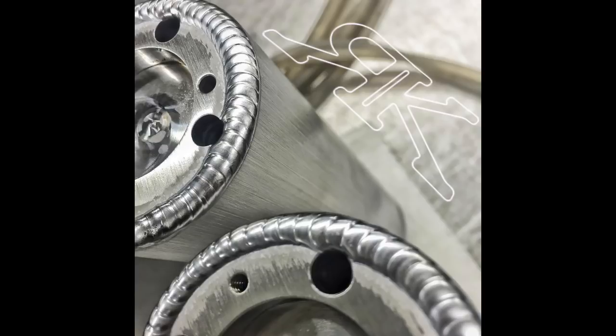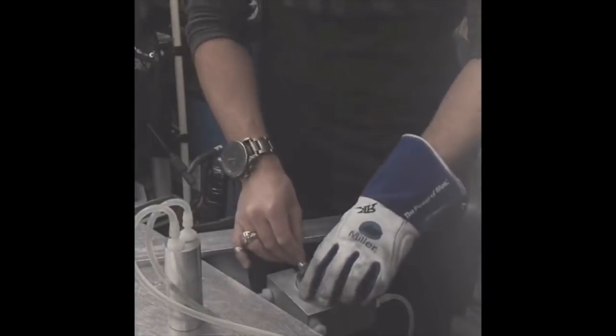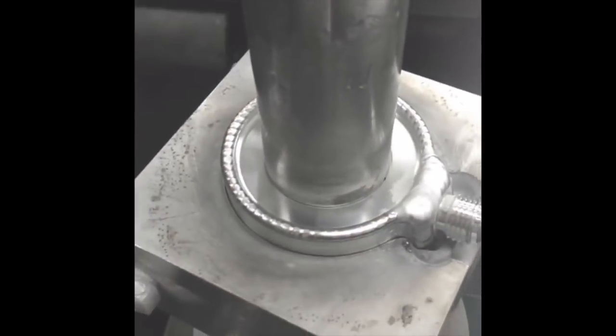If you get it welding so that you have no porosity, where everything's nice and hot and flowing really well, then you lose your mechanical properties. So that's where the helium mix and things like active TIG gas can really give you an edge as opposed to straight argon.